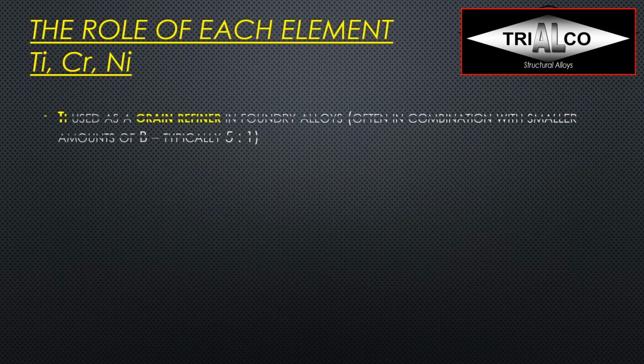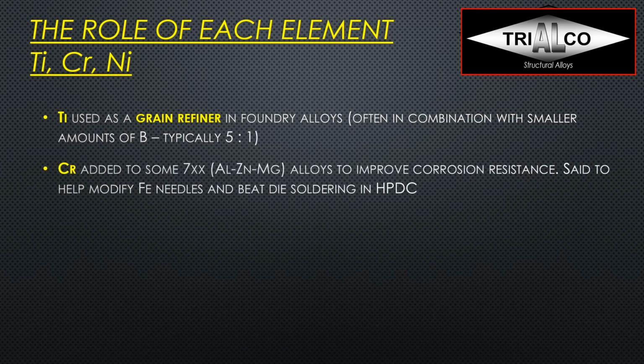If we look at the role of other elements, well, of course, titanium. Titanium is used as a grain refiner in many foundry alloys. It's often in combination with small amounts of boron, typically 5:1, and you will hear that very often, Ti-B grain refiners. And then we have chromium.